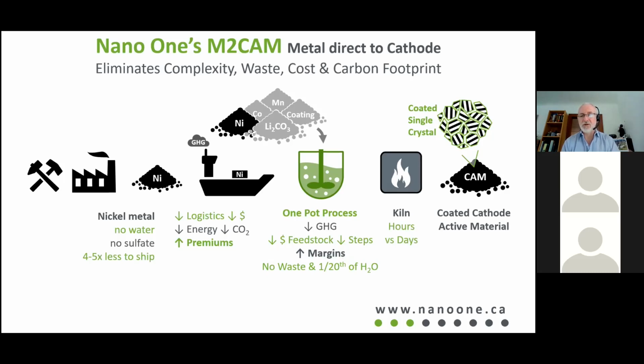The kiln is a single firing. We don't have to go through 3 days of firing and grinding. It's a matter of hours, not days, somewhere between 10 and 15 hours, I think. And then in one go, what comes out at the end is a cathode material that is already coated, and they're single crystal coated materials, which is much more durable. So this is what we can do.